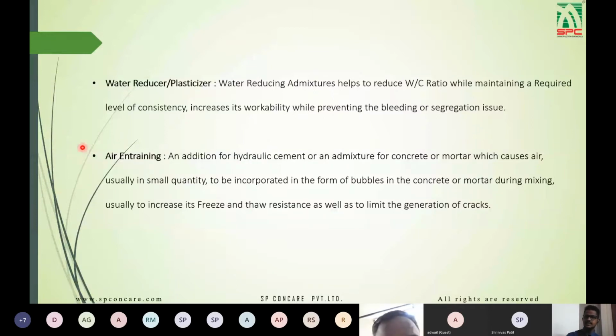The water reducer admixture helps to reduce the water cement ratio while maintaining a required level of consistency, and ultimately it increases workability while preventing the bleeding or segregation issue. In most cases, when excess water is added, the bleeding and segregation issue occurs. So to prevent that, what does the water reducer do? It reduces the water cement ratio while maintaining the required level of consistency, and then ultimately it increases workability.